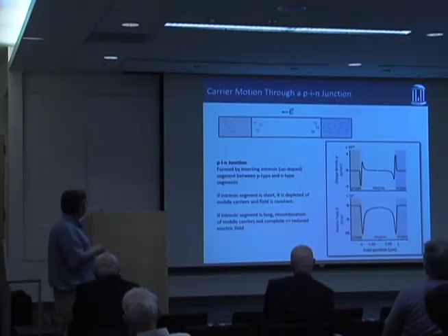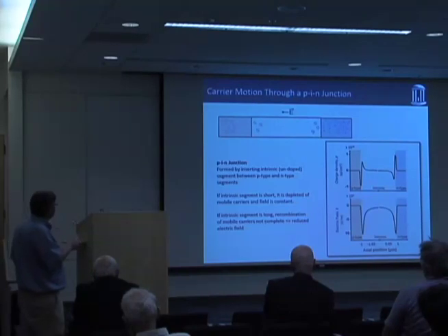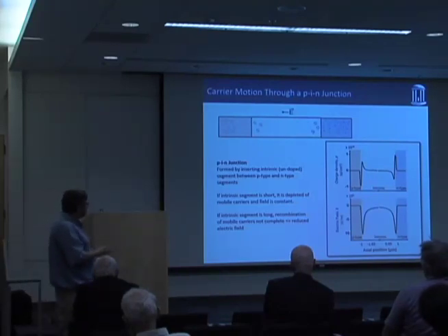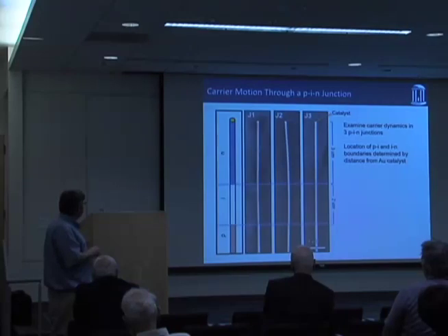And so we did the simulations on these. It's a little bit different. You don't get complete recombination of those mobile carriers. You actually get accumulation of holes at one side and electrons at the other side. So you have spikes in the electric field along the junction, but there is a non-zero static field across much of the undoped layer. And so the idea was we wanted to excite the middle of this junction and watch electrons go one way and holes go the other.